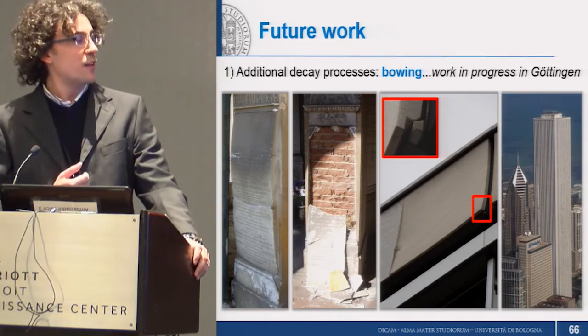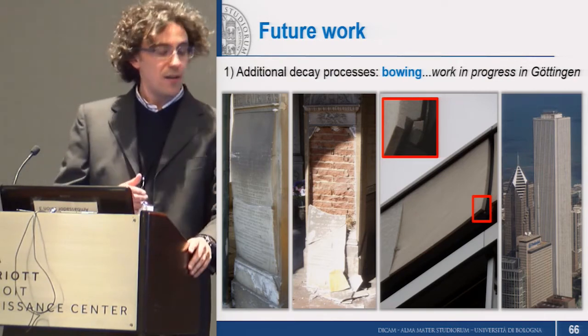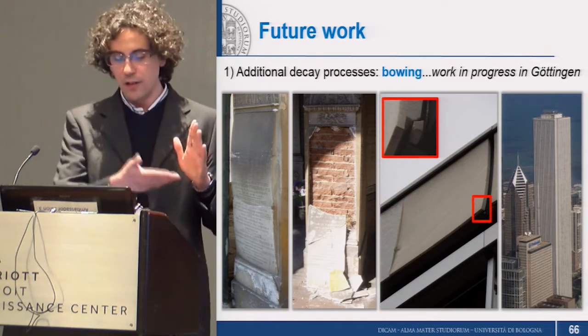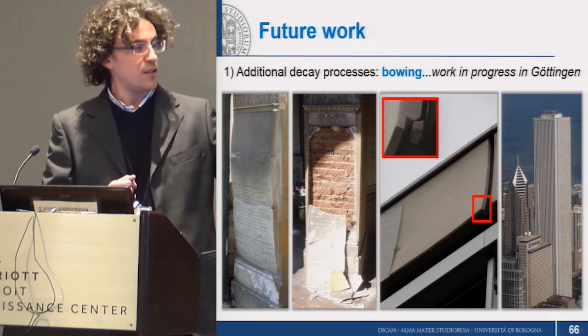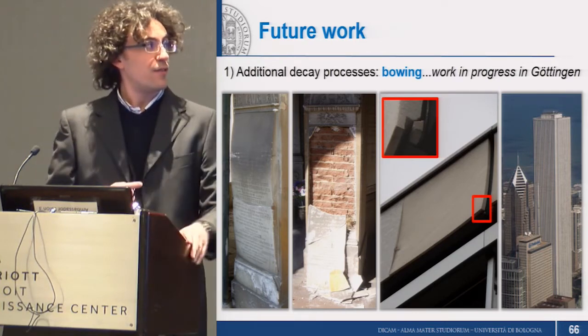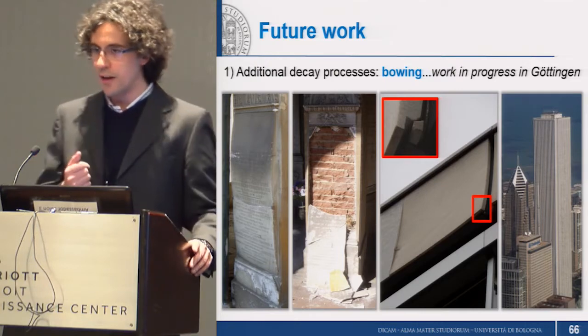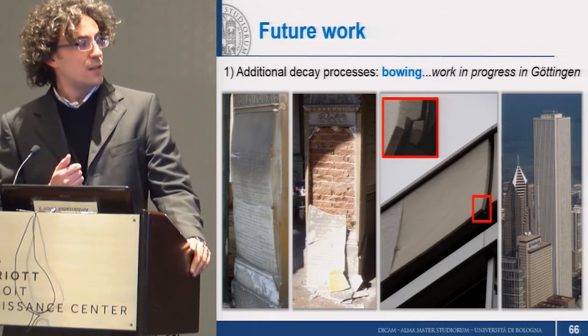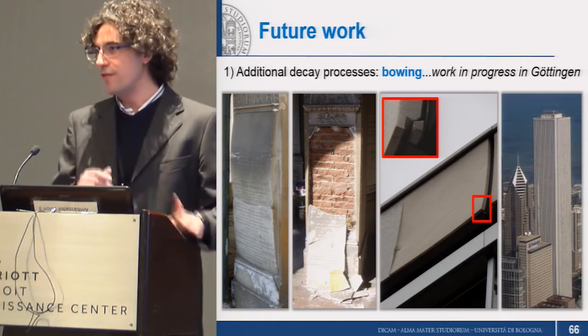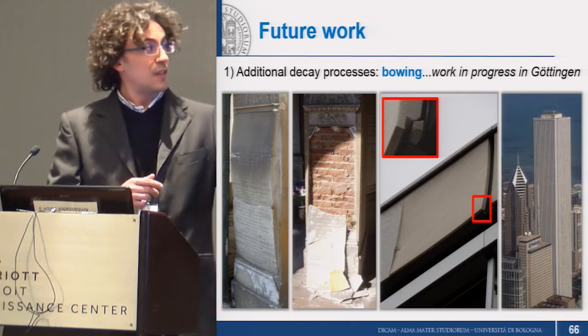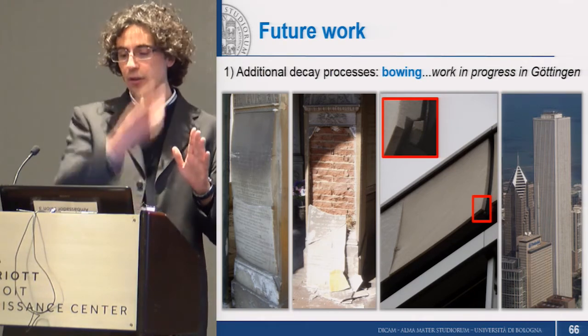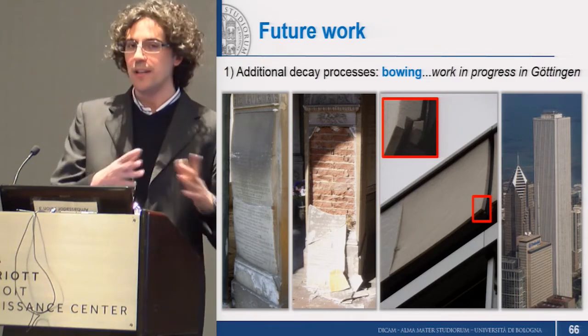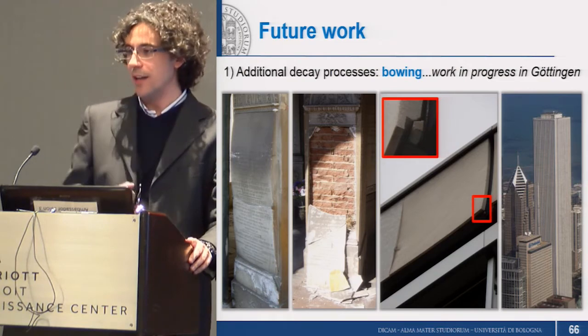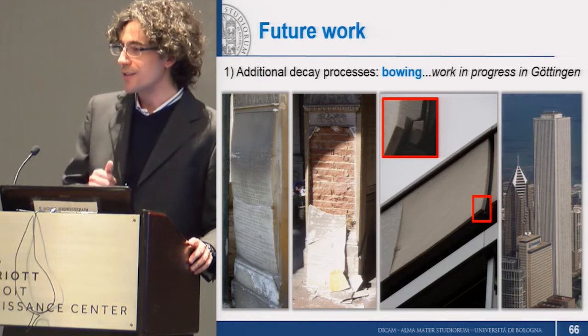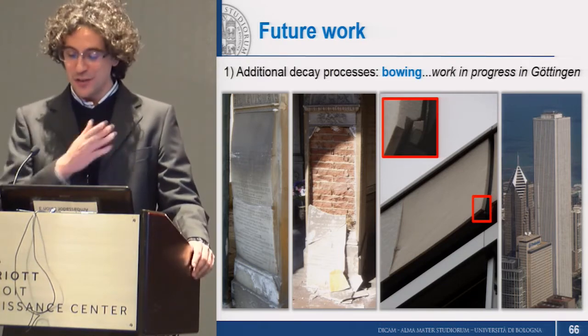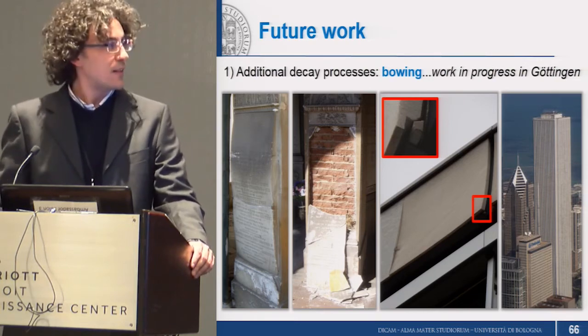So I am working in Göttingen in Germany to see if our treatment is able to arrest the bowing, which is, as you may see, literally the bowing of thin slabs that were used both in cultural heritage, but that are also often used for cladding modern facades. And this is a very important issue also for modern architecture because, for instance, on the very right, you can see the Amoco building in Chicago, which is relatively famous in our community because a few years ago slabs started to bow and fracture and fall down from the top of the building. And so they had to completely substitute all the slabs clad in the facade, which cost as much as $65 million. So I'm sure that if we are ever able to stop this phenomenon, people would be interested in it.